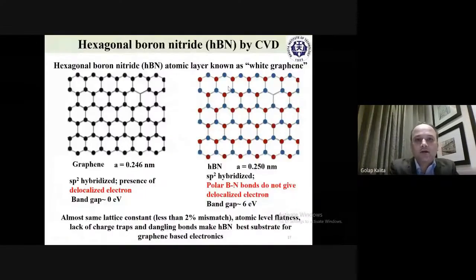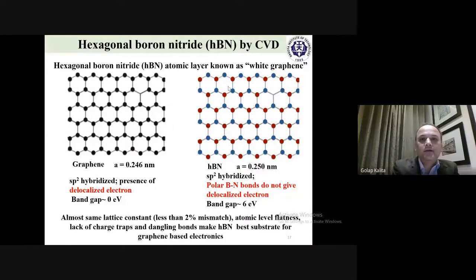Okay, then I was talking about HBN. HBN is nothing but you can replace all the carbon atoms by boron and nitrogen alternately, and you can have a hexagonal boron nitride sheet. Just like in graphene you have delocalized electrons and band gap is 0. But in sp2 BN, it's a polar BN bond and does not give delocalized electrons. So band gap is very high, 6 electron volt. Okay, and lattice mismatch is very small, so it's quite interesting.